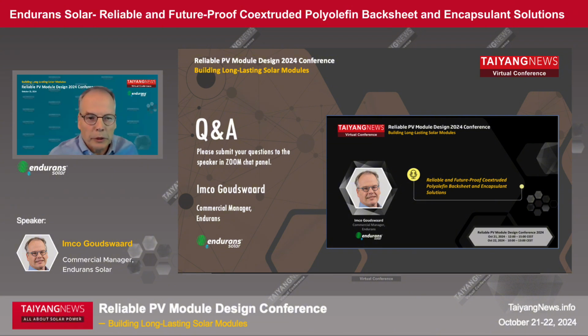We didn't test, but I guess if you make your cell gap something like 4 millimeters, then you will have a huge effect of that grid on the front side. But the gain is on the rear side, because light from the rear is diffuse, and if you have a fully transparent glass or polymer transparent backsheet, then your light trapping is less, so you get more reflection on the surface at different angles. So your low-angle incident rays will be reflected and not go towards the cell. Well, if you have a little bit of haziness, you see that diffuse transmission is going up in your film, and that captures the light also under low angles and gives you more output. And that's the 3% you see in the field.